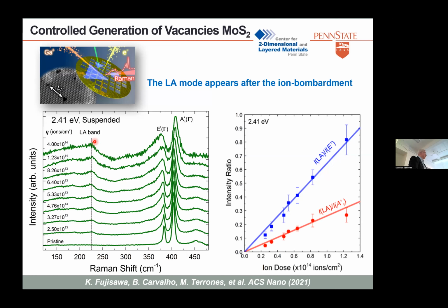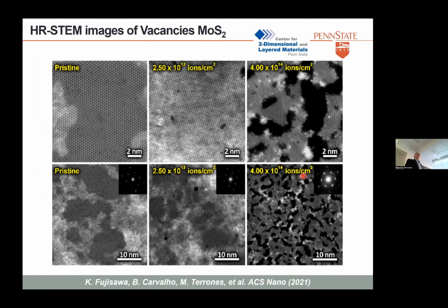And then these are vacancies of sulfur, these are vacancies of the metal. So one thing is, if you plot the intensity of the LA mode against the intensity of one of the other two modes, the in-plane or out-of-plane, you get straight lines. We measured this and we quantified it also with TEM. So this shows you the different magnifications of the treatment. The pristine one, this is PMMA that is used for depositing, and then you can see the vacancies, and you can see how damaged the sample can be, right?